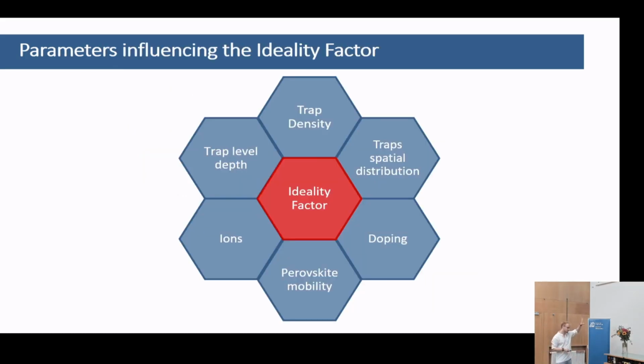So this was a conclusion just from doing that many simulations, which is also nice, because then you can get a nice picture of what affects the ideality factor. And as you can see, it's not just what type of recombination dominates. It depends on many parameters. So you should not use only this to make a conclusion on your system.